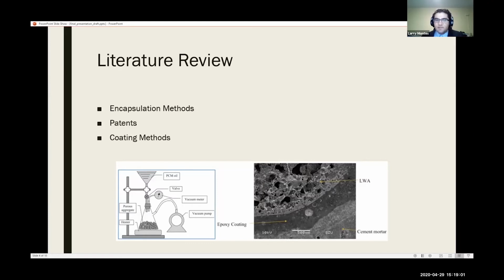However, the patents we found were all abandoned or expired, and other patents that were different enough in design allowed us to proceed. We narrowed down two main encapsulation methods for injecting PCM into the aggregates. We first have the soaking method. For this method, you submerge the dry aggregates in a container filled with melted PCM for several hours in an oven to keep the PCM in a liquid state. And you take weight measurements over time to determine how much PCM was absorbed by the aggregate.